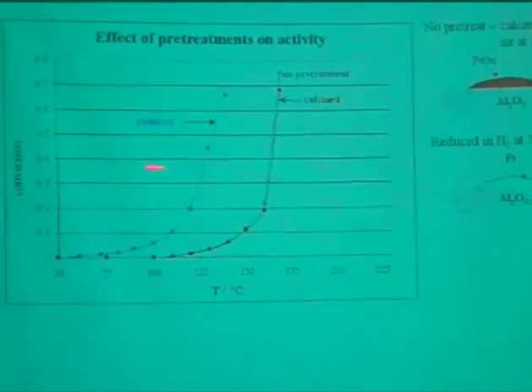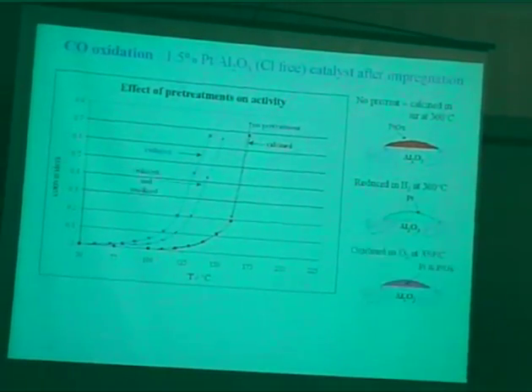Now, can we reduce the catalyst? Yes, we can, and then it's a lot more active. Okay? So again, here, depending on how you started in your pre-treatment, you end up with significant differences in activity. And so this is the reduced catalyst, and we can sort of go back and forth on this. We calcine and reduce again, but there is some resistance to the reduction after you calcine, and you need more time. In fact, I just told my student yesterday, you need 40 hours to get rid of the chlorine at 450.